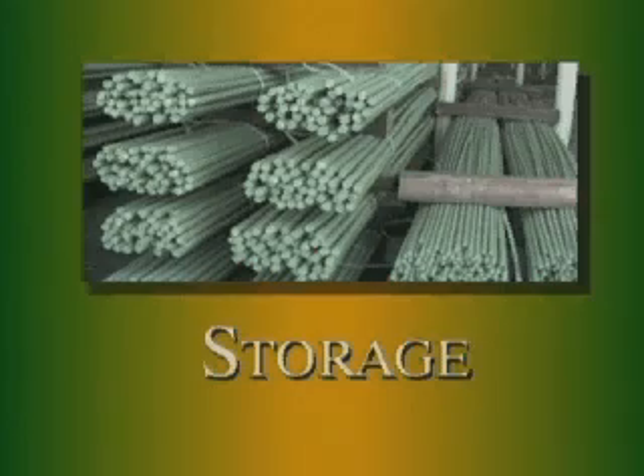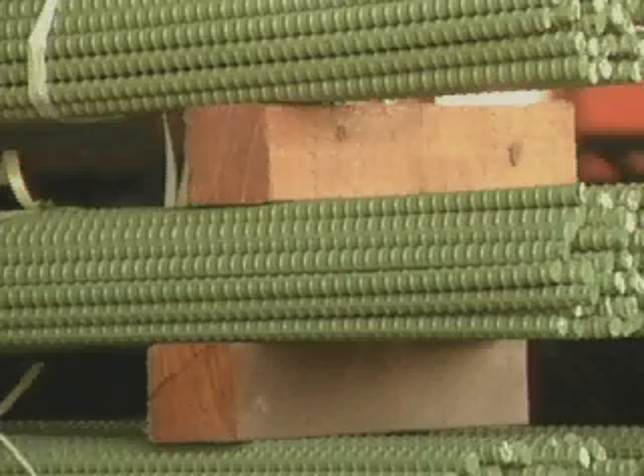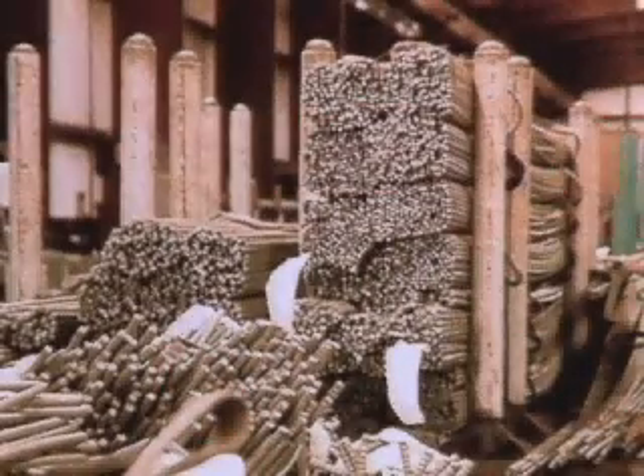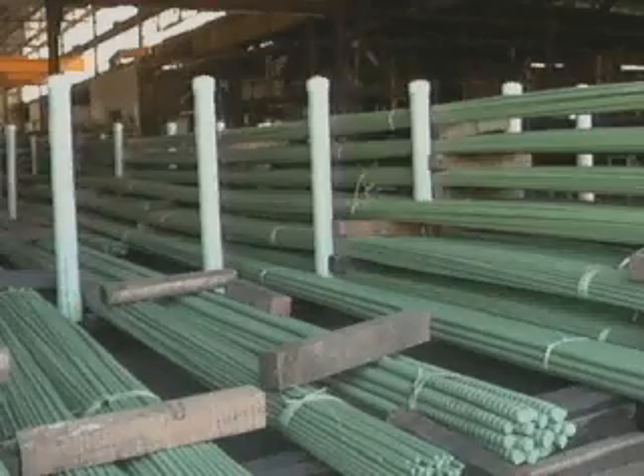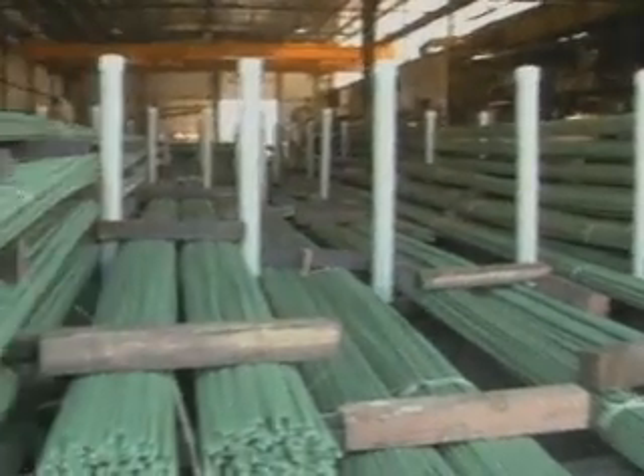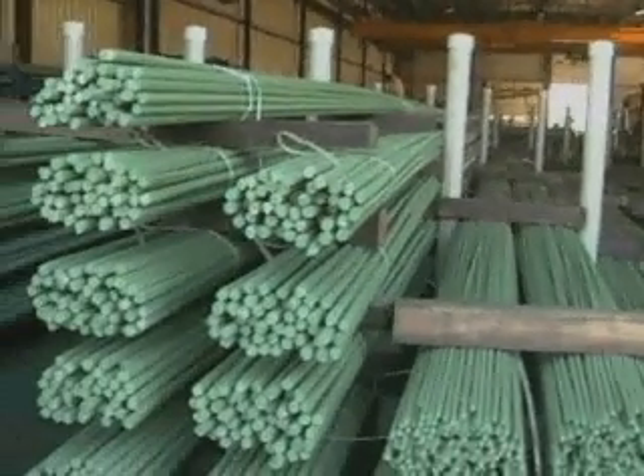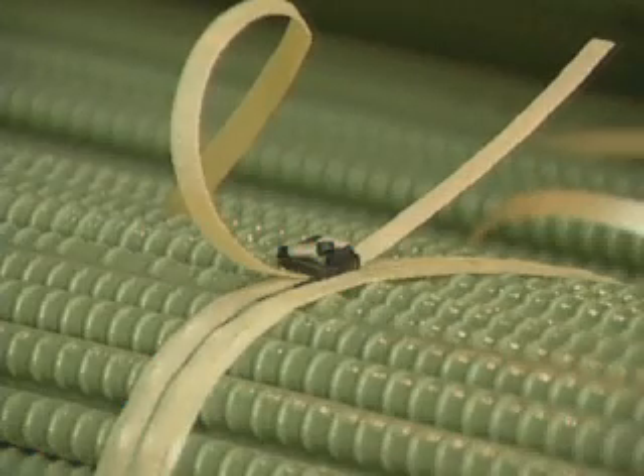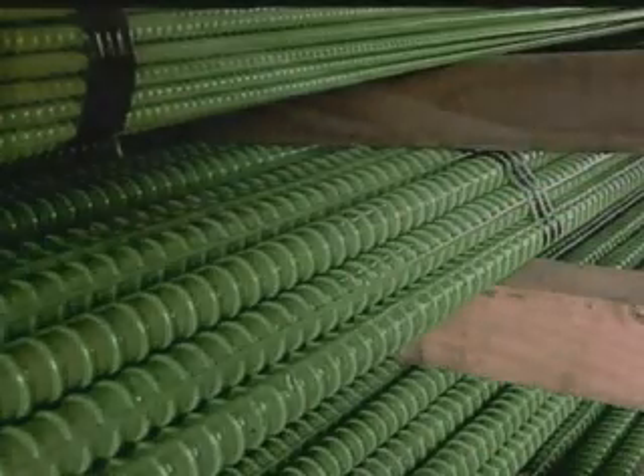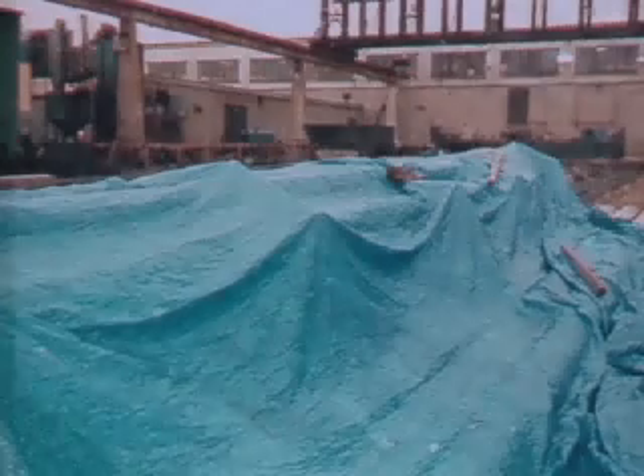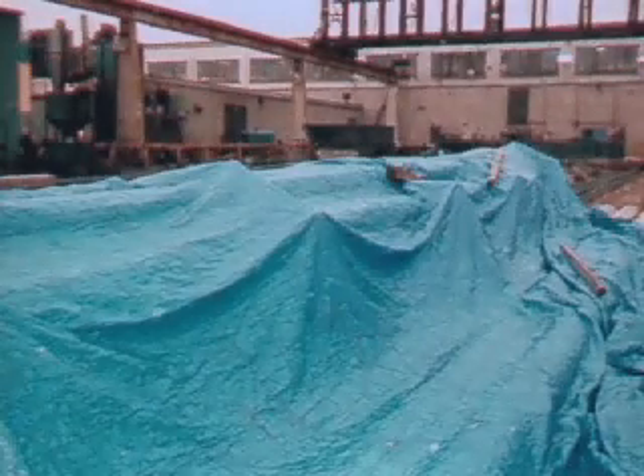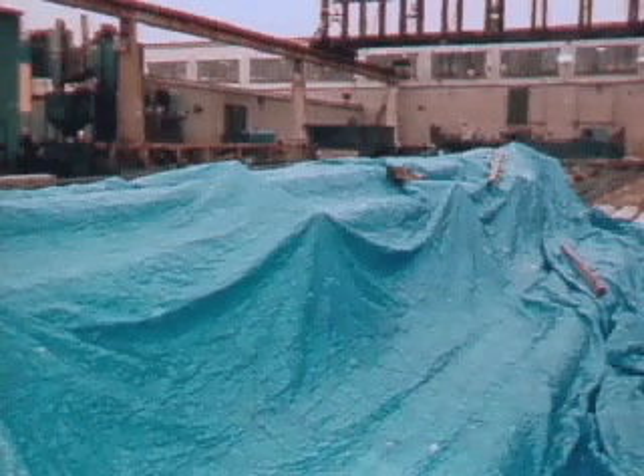To avoid damage to the rebar's coating while in storage, you'll want to store bundles above the ground on timbers or other non-abrasive cribbing. Space the dunnage close enough to prevent the bundles from sagging. Use nylon strapping or other non-abrasive material or padding to bundle bars. If you're storing outdoors, coated bars should be covered with polyethylene or other suitable covering. Make sure that it's placed in a manner that allows air circulation and minimizes condensation on the bars.